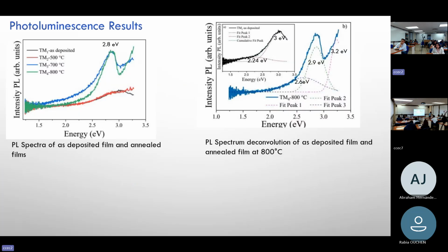Well, photoluminescence results. In this picture, we can observe the photoluminescence intensity of as-deposited and annealed films. We can observe the as-deposited intensity is comparable to the annealed film at 500 degrees Celsius. The film annealed at 800 degrees shows great intensity at 2.8 electron volts. However, deconvolution is necessary to know the band positions.